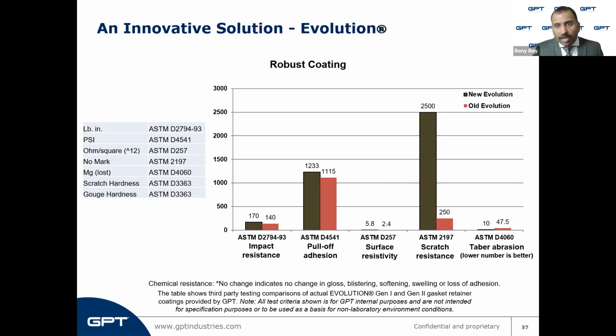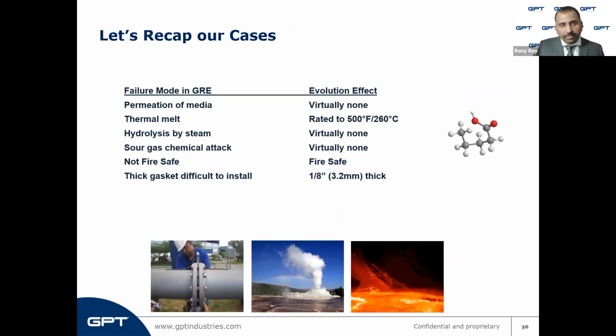But you can see another graph in brown color. It was the second edition of this coating, which we improved further with more additives to make it stronger and more resistant to the site conditions. And you can see that that new combination is much better than the old combination, which was already better than all the coatings that are available in the market. It is 10 times stronger than the older coating. So in short, this coating that has been used on this gasket is very, very scratch resistant and highly durable compared to any other coating that you have seen available in the market.